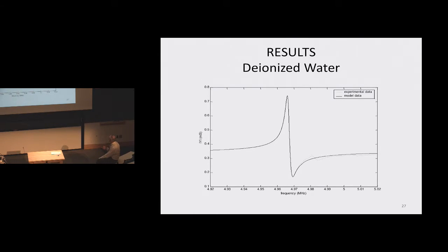Well, this represents a measurement of the admittance using a network analyzer as a function of frequency. This corresponds to the peak here. This is admittance, so this corresponds to 1 over impedance. This is the location of that transverse shear mode, somewhere around here in frequency. The experimental data is given by the curve you see here. This is almost indistinguishable. And there's the model data right there. So what it basically means is that this equivalent circuit, which you obtained through the solution of these coupled equations, appears to agree reasonably well with the experimental results.